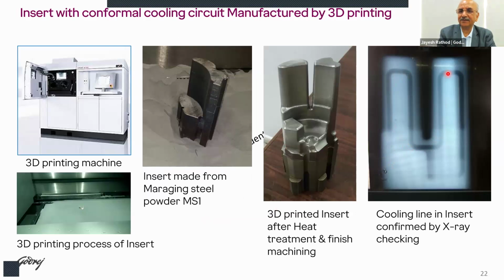channels. What you can see here is after the insert is 3D printed, we have done the X-ray just to see whether the cooling channels are in the right place, and that they are not very close to the surface where a puncture may happen. This is the machine which has been used for making this 3D printed insert. This is after additive manufacturing. The piece looks like this, and after the final finish machining, it looks like this.